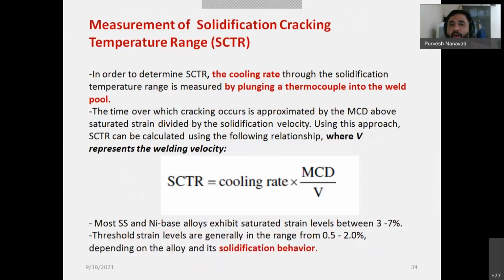Now, measurement of solidification cracking temperature range. That is most important. If you remember, I mentioned that there will be a certain range, from the TL to TS, from the liquidus temperature to the solidus temperature, which is the most susceptible range. It is the most dangerous range in which there is the highest susceptibility for a crack to occur. So this SCTR, solidification cracking temperature range, can be calculated using this formula.